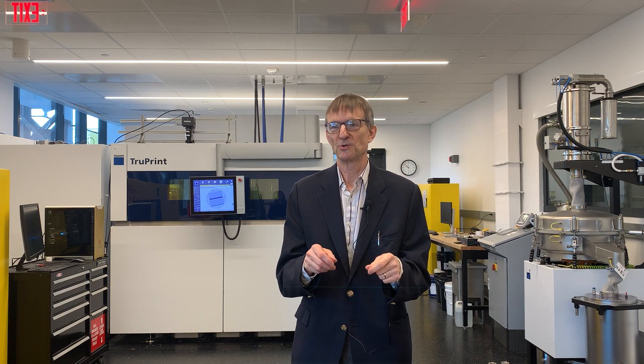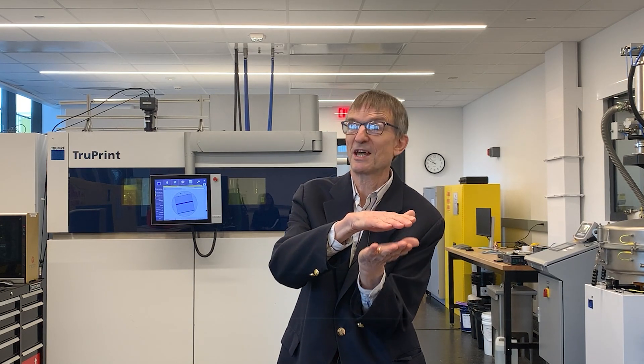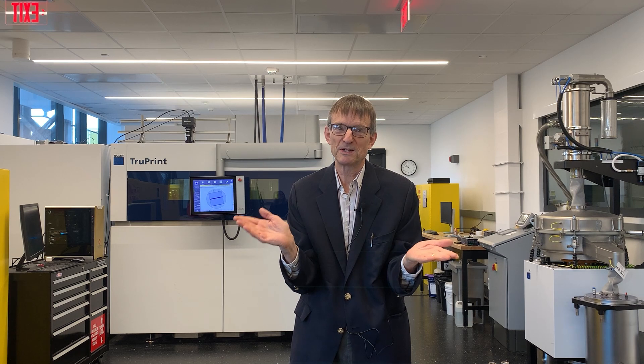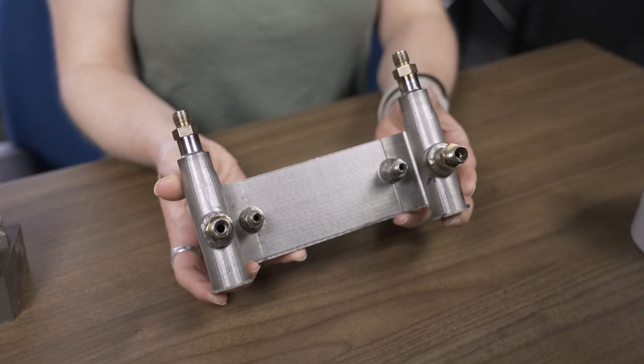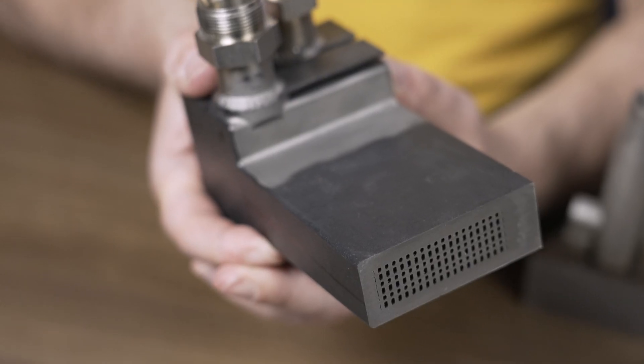Unfortunately, it is quite difficult to do quality control to guarantee that every place that needed to be bonded really is bonded. The other problem is that these are pressure vessels under tensile stress — an opening stress. If there's anywhere the bond didn't work, what you have is basically a narrow crack, which is a stress riser, a stress concentrator, and a place where it will start to fail. The experience with these was not good — they would commonly fail prematurely, long before their intended life. The lifetimes expected of these kinds of units are at least 10,000 hours, preferably even longer. That's why 3D printing became the fabrication method of choice.